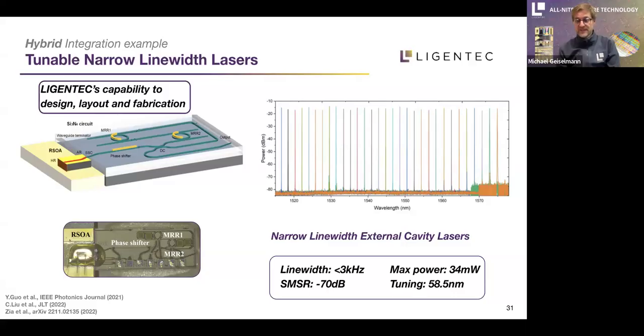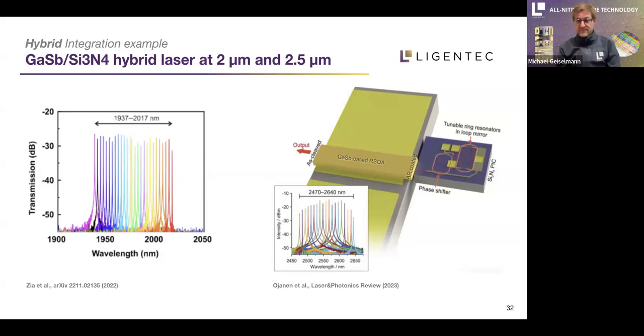You have a very good power output, very good signal to noise, and you have a very large tuning range of your laser, which is given that we integrate again here heater phase shifters onto the low loss nitride platform to get access to tuning of the laser wavelength. And as I mentioned initially, this can be done in C-band, but that can also be done for different wavelength regions, either on the shorter or the longer wavelength regions.